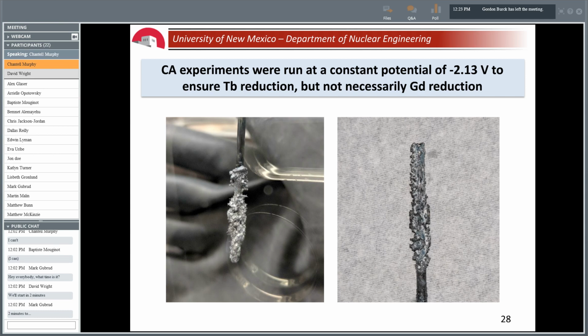So these are some of the best looking deposits, I would say, that I was able to get. But the first picture is from round 8, run number 8, which is the 1-to-1 ratio. And then this deposit is from another set of experiments with a 100-to-1 ratio. Both of these were dissolved in nitric acid, 20 milliliters, and I will run ICP atomic emission spectroscopy on them, hopefully later today, and I will figure out exactly what I got. Probably going to be terbium, but maybe also gadolinium.